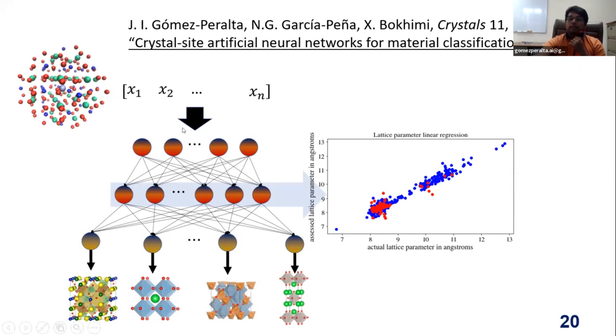This artificial neural network was developed with up to 8,000 compounds. And these compounds were described with up to 6 different chemical environments or Wyckoff sites. And this gave place to 163 features. The compounds were classified by the artificial neural network in up to 10 different crystal structures. And after training the artificial neural network, we used the features built by the hidden layers to establish a linear correlation with the lattice parameters of compounds having the structure of garnet, spinels, perovskite in the cubic, orthorhombic, and rhombohedral symmetries, as well as Ruddlesden-Popper structures. And the lowest correlation coefficient that we got after establishing this linear correlation was 0.95.